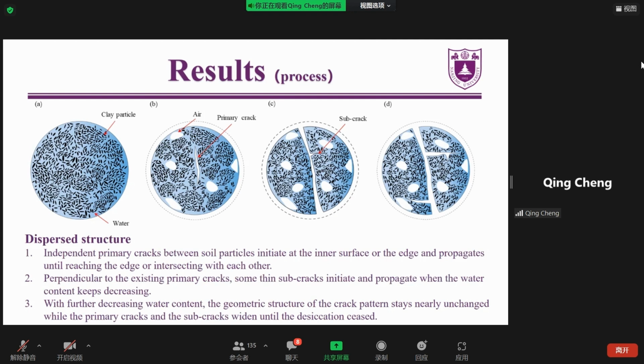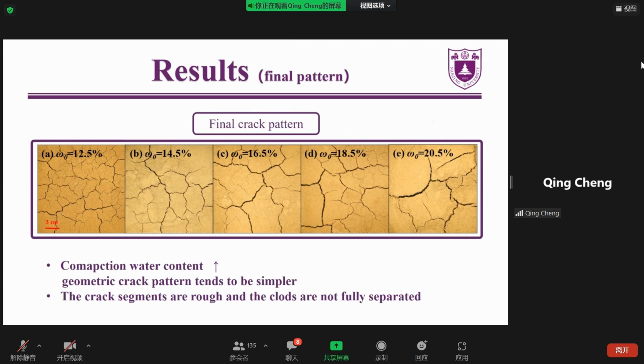And the third stage is, with further decreasing water content, the geometric structure of the crack pattern stays nearly unchanged, while the primary cracks and the subcracks widen until the desiccation ceases. And this slide shows the final crack pattern of each soil sample. We can find that there exist more fine and thin cracks in the soil samples with lower compaction water content. This represents that there are fewer weak zones in the soil sample with a higher compaction water content.